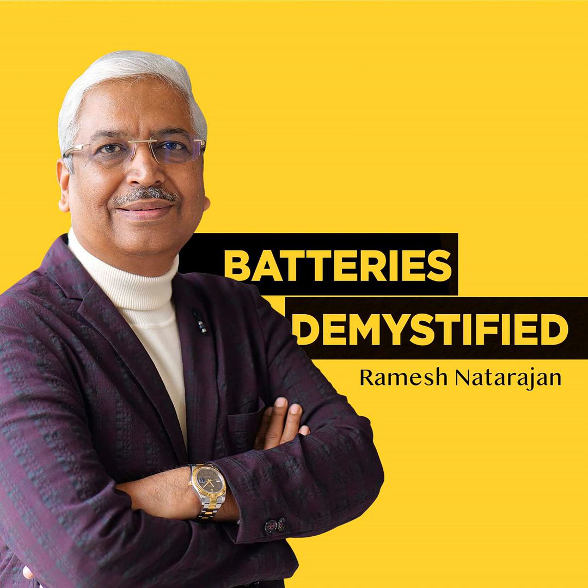Is it possible that Vanisperse can leach out of the plates due to overcharge or high temperature? Again, this really gets back to that fundamental understanding that we're trying to pursue in a very active sense in our R&D teams. Vanisperse A is really interesting because at high temperature, it actually has lower solubility than at low temperatures. That's fairly uncommon, but it's due to the biopolymer structure that drives that insolubility. Whereas with Vanisperse HT1 and Vanisperse DCA, we actually see higher solubility at higher temperatures, as one normally would expect. So then thinking about how at high temperatures we might be losing more, it's a very interesting system to try to think about.